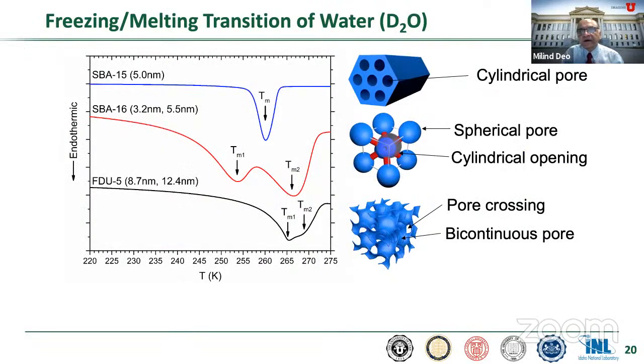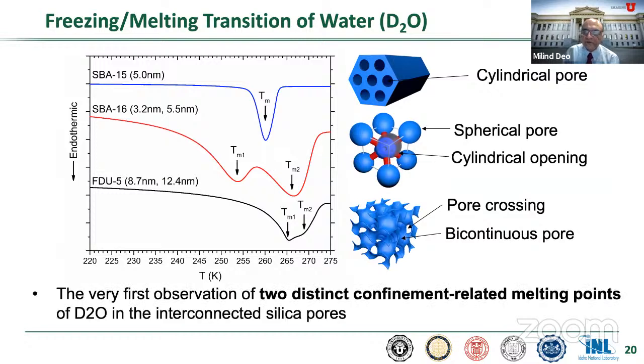So we went ahead and did some experiments of freezing or melting transition of water in the materials that we ourselves made. This one is, I think, SBA15 with the cylindrical channels, SBA16 with this bimodal structure, and then FDU5, which also has a pore crossing bicontinuous pore, which is all made by us in our center. And for the first time, we were able to see these two transitions for SBA16 and for FDU5, and one transition for SBA15.